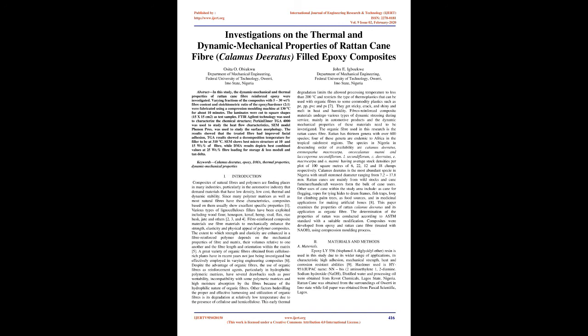FTIR Agilent technology was used to characterize the chemical structure. PerkinElmer TGA 4000 was used to study the heat flow characteristics. SEM model Phenom ProX was used to study the surface morphology. The results showed that the treated fiber had improved interfacial adhesion.